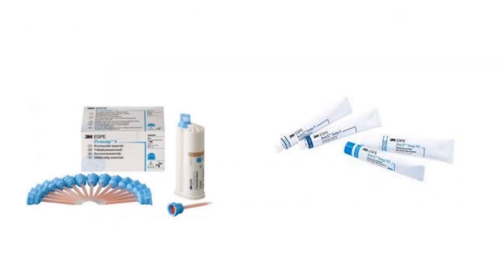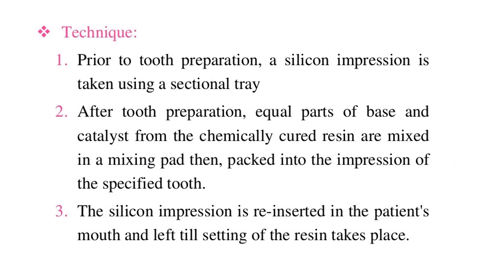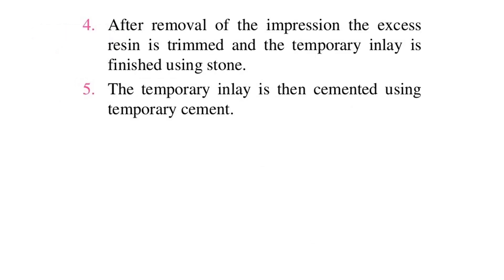They are cemented using temporary cement. Technique: (1) prior to tooth preparation, a silicone impression is taken using a sectional tray; (2) after tooth preparation, equal parts of base and catalyst from the chemically cured resin are mixed on a mixing pad, then packed into the impression of the specified tooth; (3) the silicone impression is reinserted in the patient's mouth and left until setting; (4) after removal of the impression, excess resin is trimmed and the temporary inlay is finished using stone; (5) the temporary inlay is then cemented using temporary cement.